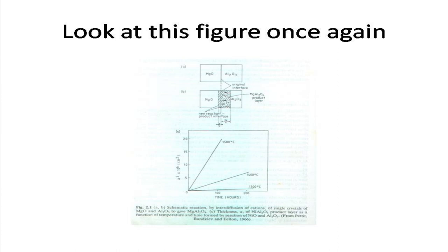Now, how do we compute these reaction rates? We compute the reaction rates by measuring the thickness x of the spinel product layer in the figure that we have seen, and x squared, that is the thickness of the layer squared, is plotted against the time. And when you plot this in part C of the diagram, you will find that you always have a straight line: 1300 degrees centigrade, 1400 degrees centigrade and 1500 degrees centigrade.